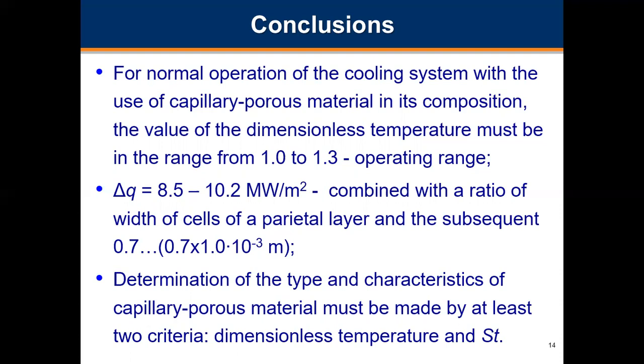In the operating range, delta Q equals 8.5 to 10.2 megawatt per square meter, and operating interval theta equals 1.25 to 1.30. The following capillary porous materials are possible, combined with a ratio of width of cells of a parietal layer and the subsequent 0.7 times 10 to the power of negative 3, single layer with cell width 1 times 10 to the power of negative 3, two layer with a layer thickness and width of wire with width of a cell 0.02 times 10 to the power of negative 3 meters.